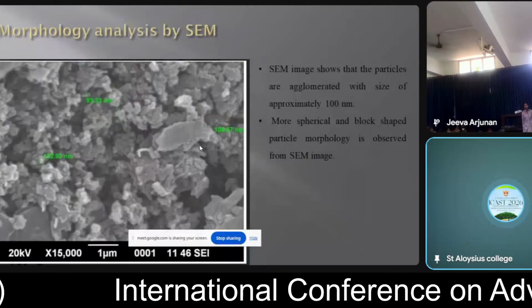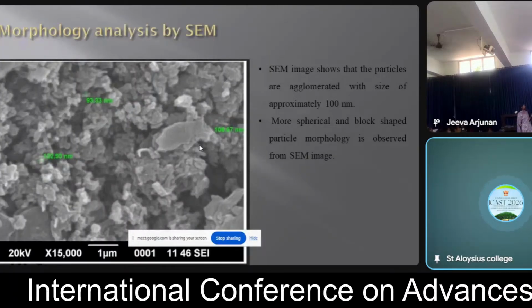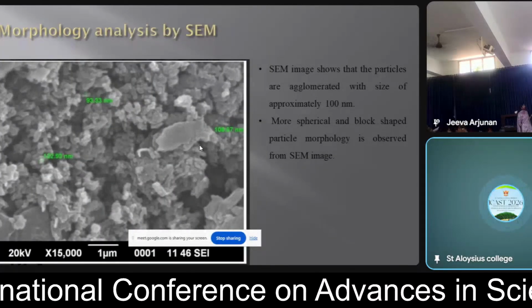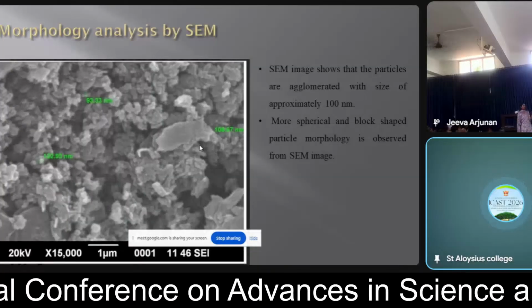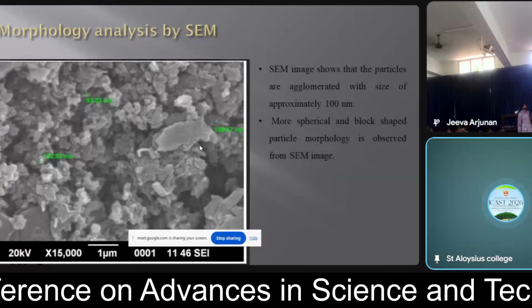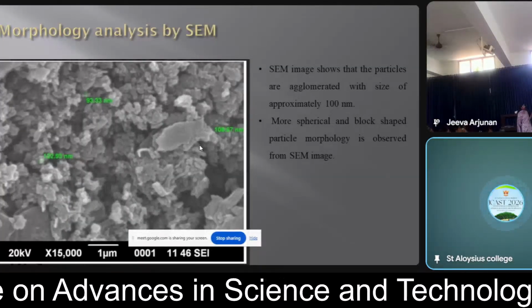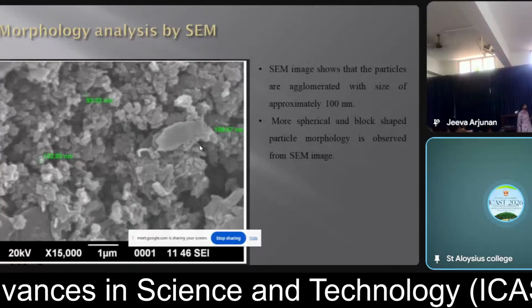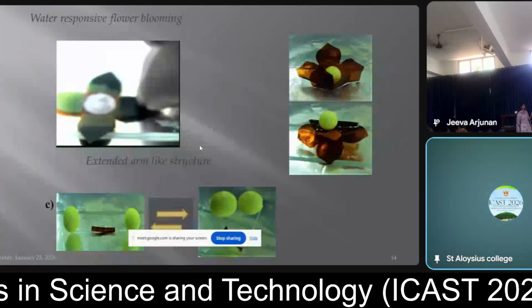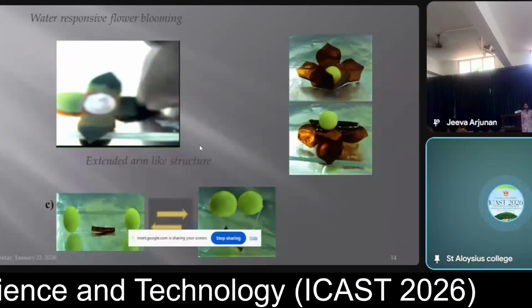So we did SEM. From the SEM images, we analyzed that the size of the particles is 100 nanometers, which we also got from DLS. And there are more spherical and block-shaped particles in the morphology. So this is what we did in the experiment.